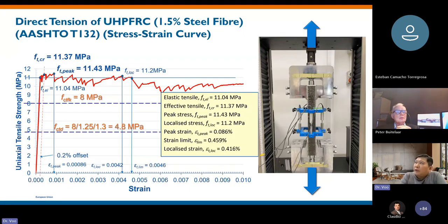Okay. Here is the experimental curve of the UHPC which we use, and this is the direct tension test based on the AASHTO method. So with 1.5% of steel fiber, the UHPC will have a first crack around 11 MPa, and you can see that after the crack, it will continue to deform, and the peak is also around 11 MPa.